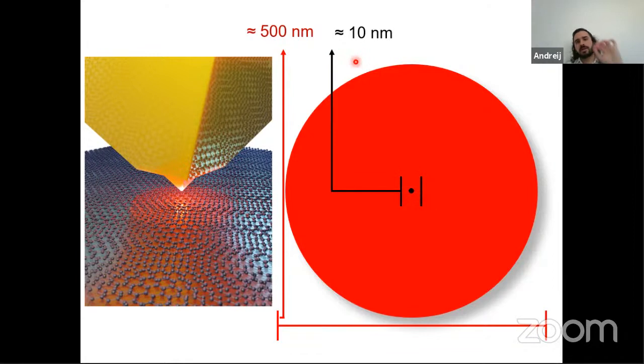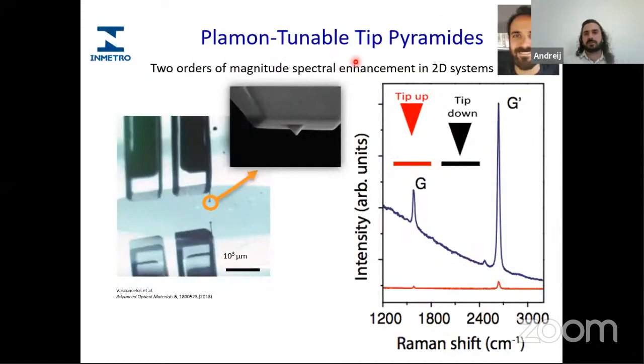So the nano antenna breaks the diffraction limit of light, and now we can observe optical phenomena at the nanoscale. And in addition to that, the nano antenna enhances all the optical properties of it. And the larger the enhancement, the better the tip. We use special tips made here in Brazil now by our group and in partnership with Inmetro and Thiago, which we call plasmon tunable tip pyramids.